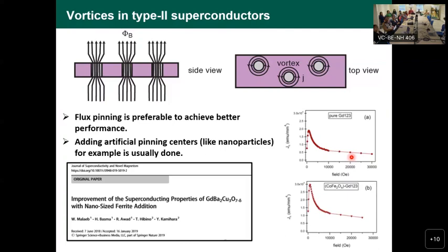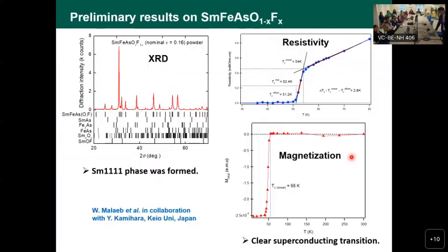Of course, for iron pnictides it's more challenging, because you first have to prepare the system and then add the nanoparticles; each challenge is a thing by itself. Anyway, we did some work on that project. We prepared this iron-based superconductor at Keio University with the Kamihara group, and judging from the X-ray diffraction data we could reach the phase. We could also see a very nice superconducting transition, as you see here. These are the experimental results, and this is confirmed not only from resistivity, but also from magnetization. So we completed the ID of our new superconductor.